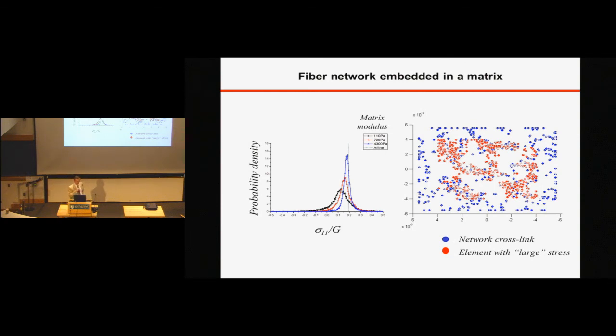What happens with stresses in the matrix when you put the network in? You are going to get a distribution like, for example, the black one. So the first observation is, although you are stretching in the one direction, so your global stress is positive, right? You are actually getting stresses in the matrix which are negative. So you see this tail extending to negative numbers, right? So you actually get compression while you stretch this way, okay? Well, maybe not that surprising because we know that this must be heterogeneous. So, okay, maybe it does happen, all right?